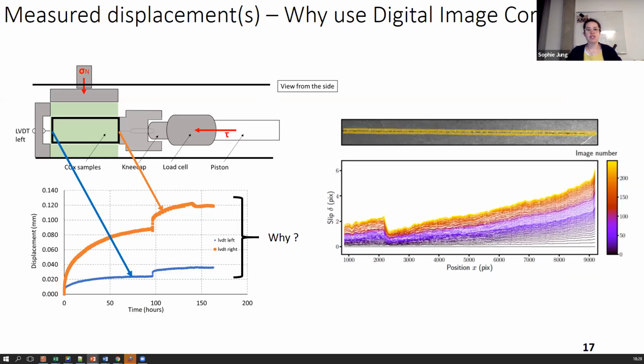So why do we use digital image correlation, as it's not that easy to implement? It's because, as you can see on the left side of the slide, the data given by the LVDT gives only the average displacement or deformation of the central block. So you see that there is more movement where we are pushing than on the other side, but it's certainly because we are measuring with those LVDT both the behavior of the rock matrix and the behavior of the fracture, and only with this information it's very hard, I think maybe impossible, to separate the behavior of the fracture from the behavior of the rock matrix.